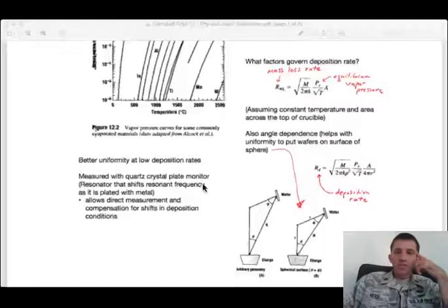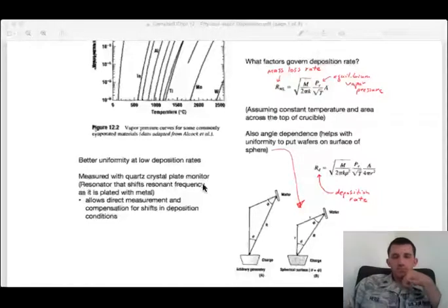It's a simple setup, but even if you pick a high melting point, you're still going to be driving off some of the atoms of your filament, which is a degradation mechanism. It also means that as you have higher and higher melting points, it becomes less reasonable that their vapor pressures will be much higher than your deposited metal or than your heater filament.